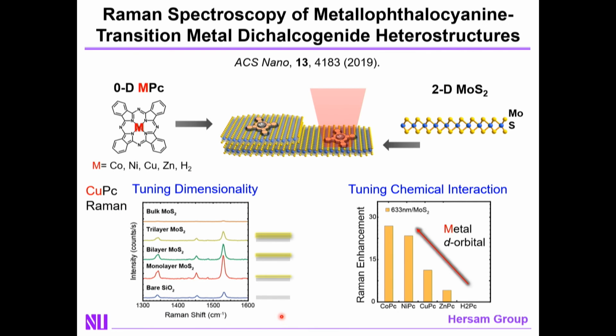Additionally, you can look at other effects, such as Raman spectroscopy. One thing that you observe in Raman spectroscopy is that the degree of Raman enhancement of the molecular vibrational modes depends upon the dimensionality of the underlying substrate. If I were to put a metallo-phthalocyanine on bulk MoS2, I can barely see the vibrational modes of the metallo-phthalocyanine. However, when I thin down to the monolayer limit, we see significant Raman enhancement, and the peaks become evident.